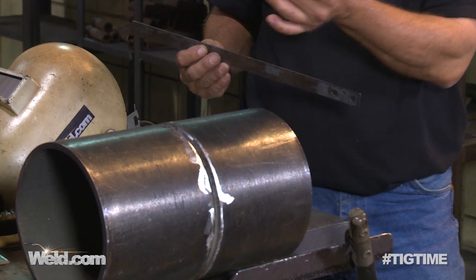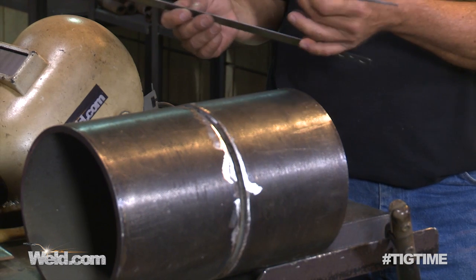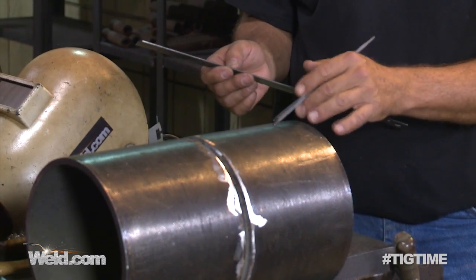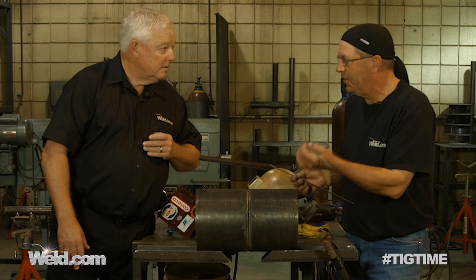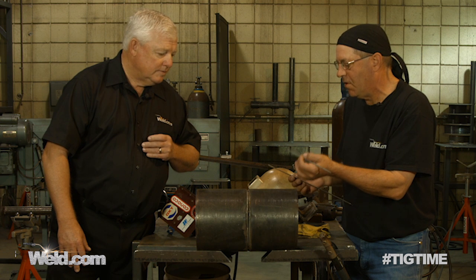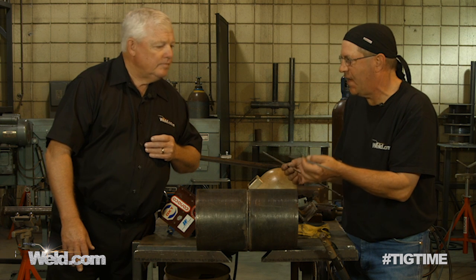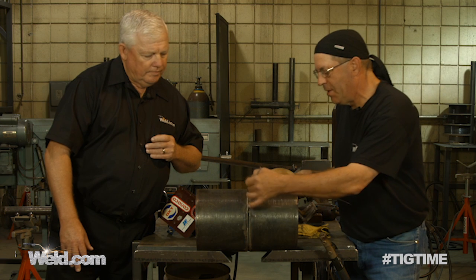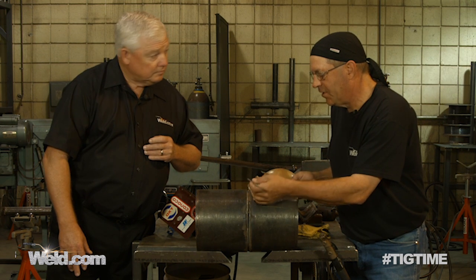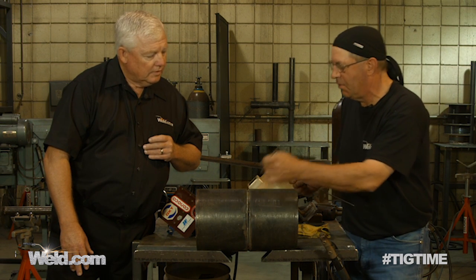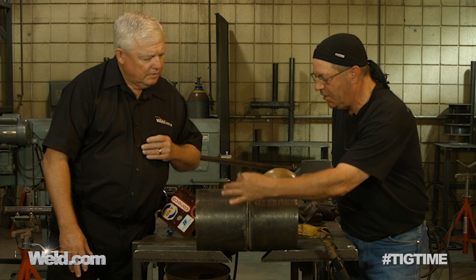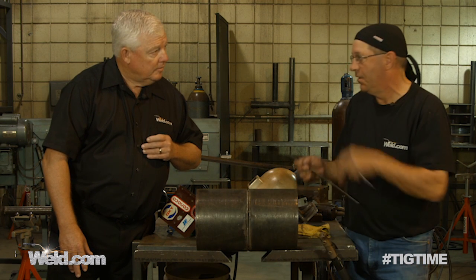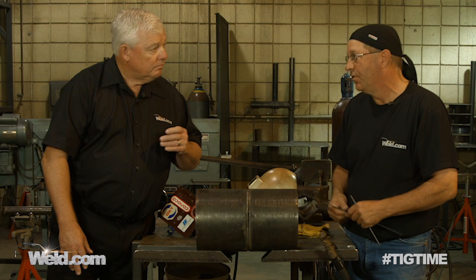This is E6010, 6010, 7010, 8010, depending on the alloy of the pipe. So this violent digging type of arc that we have, we consider this a fast freeze electrode. I'm able to create the arc. It actually blows a keyhole around the end of the rod, and I can force this in here and just fly downhill, and it's fusing the inside.